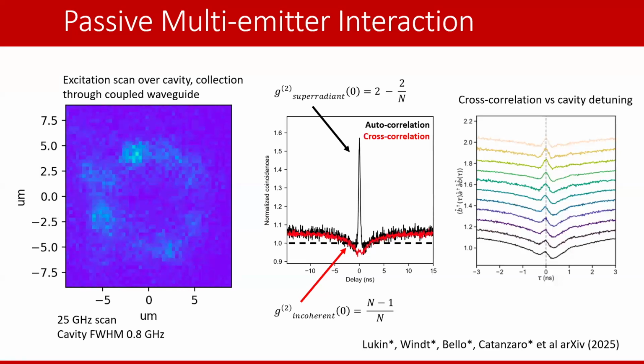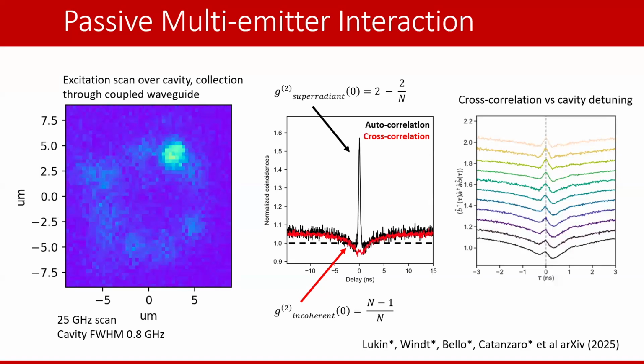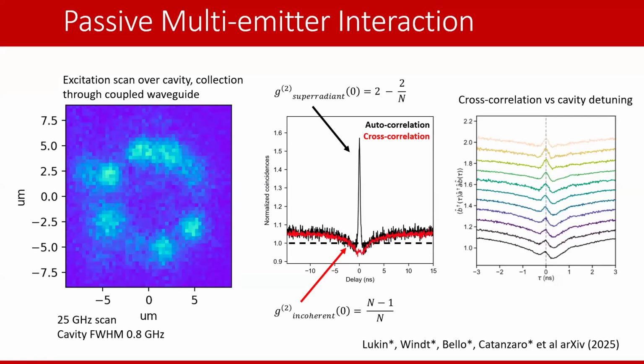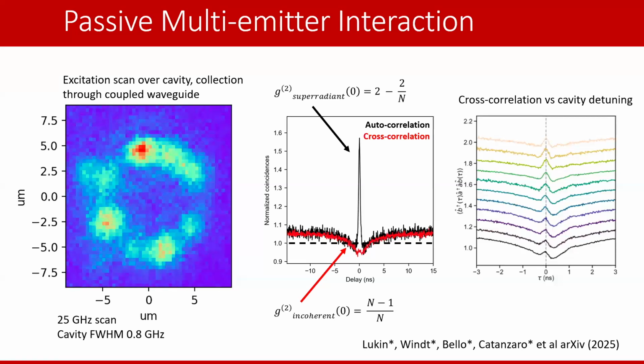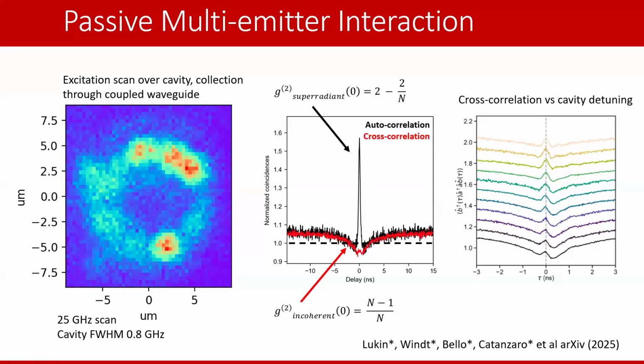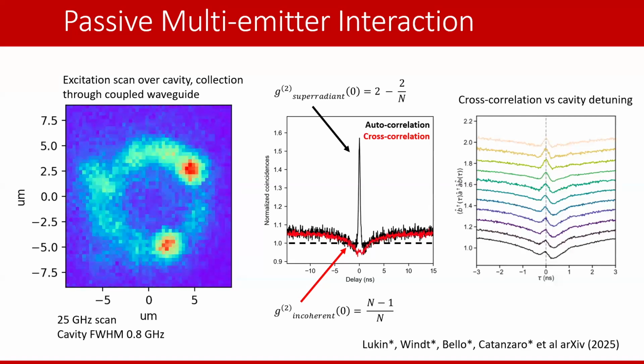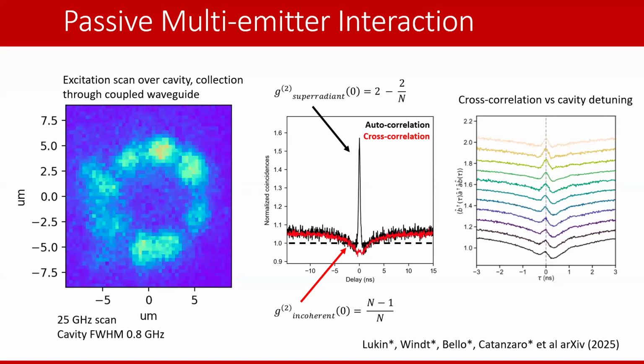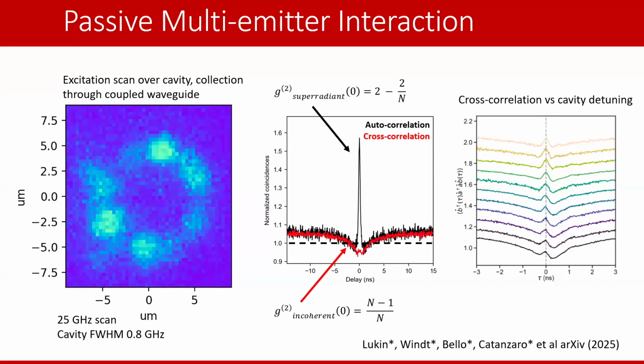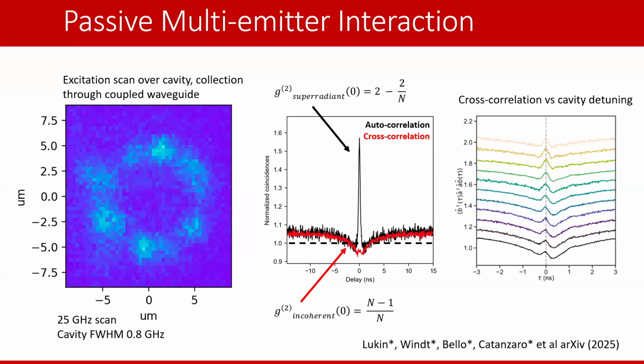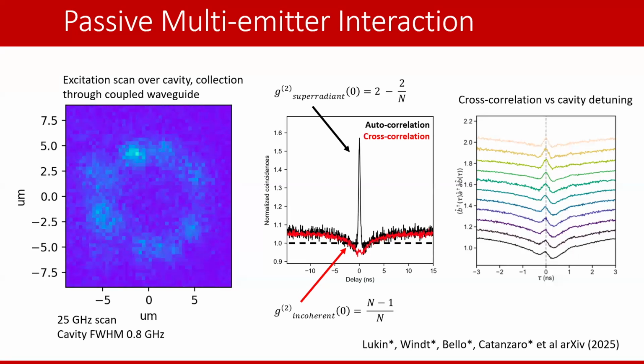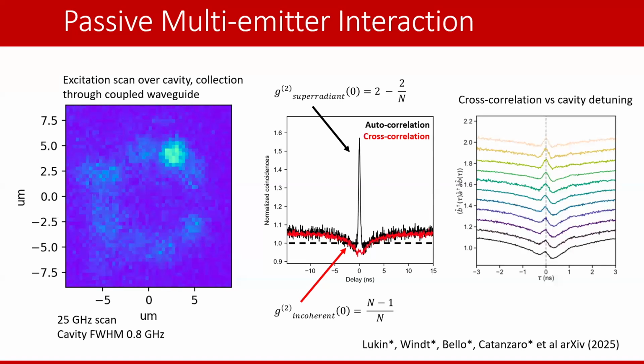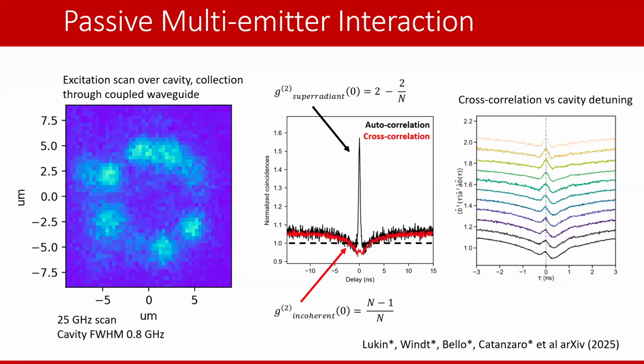And what you're seeing as they show up in time is gas tuning the cavity through several central frequencies. That's why the defects are not all there at the same time, because again, like I mentioned before, this distributed environment, the moving charges in the environment, the changes in the lattice mean that not all of our qubits are the same. They're at different spectral positions and they move in time. So that's why you see this sweep through them. And then because the defects are in random positions around the resonator, and moving in time, this has a spectral disorder and a phase disorder between the defects within the cavity.